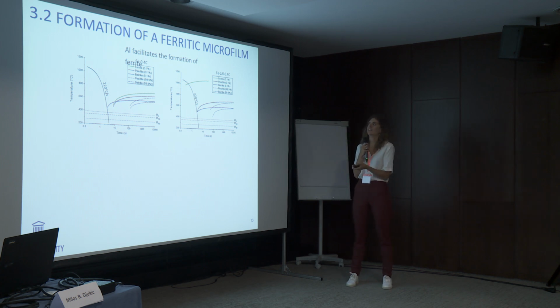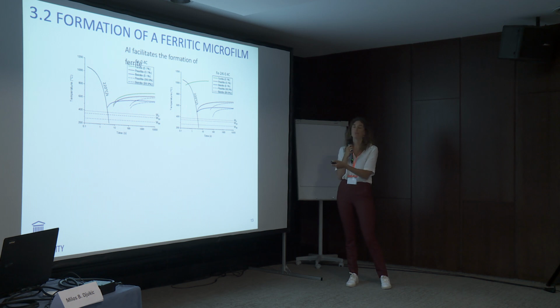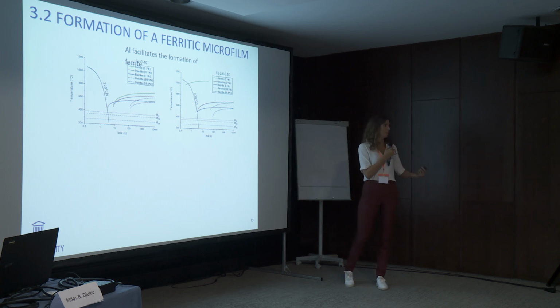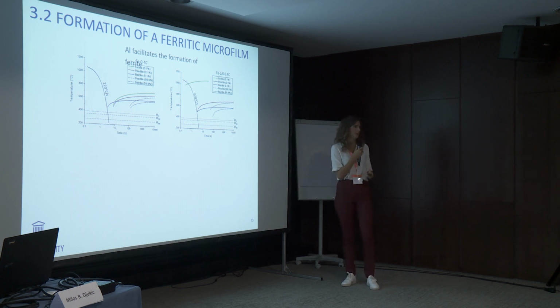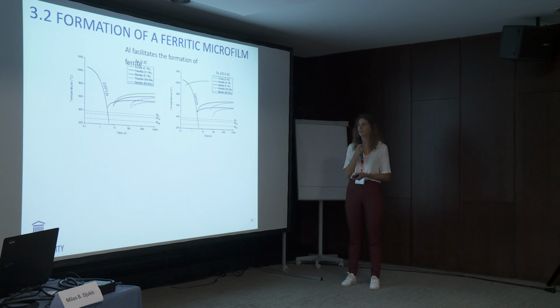And the nice thing about this is that we can already form ferrite just by a very simple quenching treatment. This is in fact very peculiar because normally ferrite is introduced by a more complicated heat treatment, but just by adding aluminum, you can really form ferrite just by simple quenching. How does the microstructure look then?